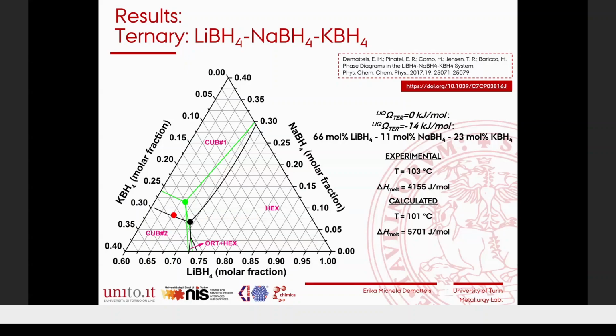system. And what we observed was the formation of a ternary eutectic with a really low melting temperature, as low as 103 degrees C. And we were able to define well the composition of this ternary eutectic, which in the literature was already proposed, but it was not really the good composition. So by extrapolating and also by new experiments, we were able to define this temperature. And by introducing a negative interaction parameter in the description of the Gibbs free energy, we were able to extrapolate the liquidus temperature evidence in green and find the right composition of this eutectic.